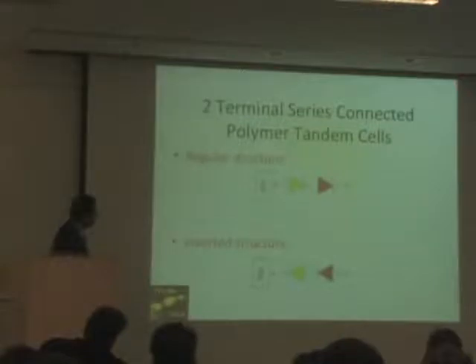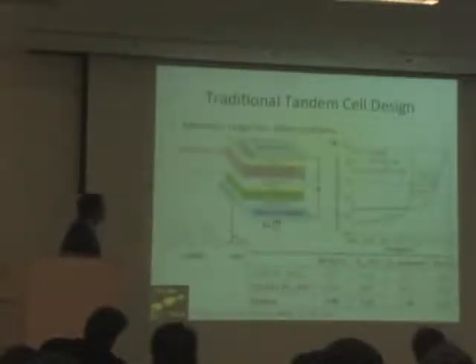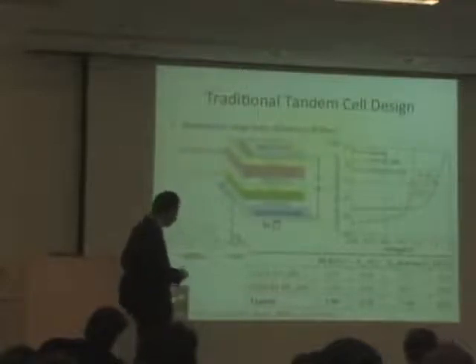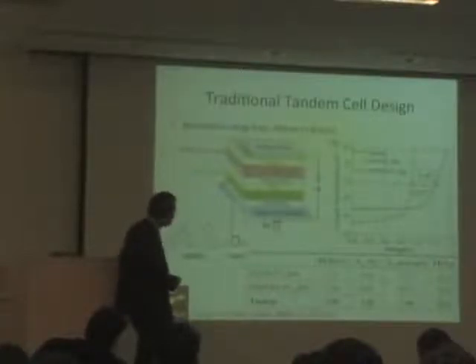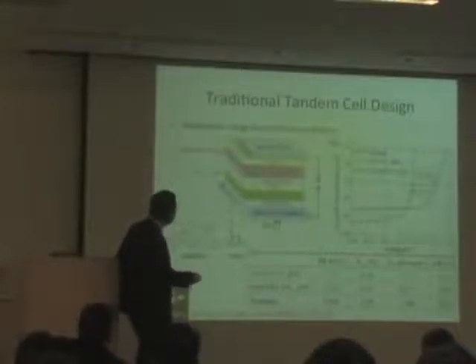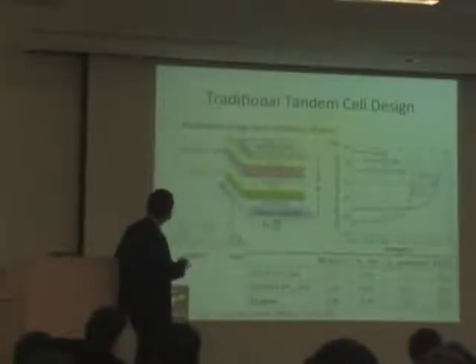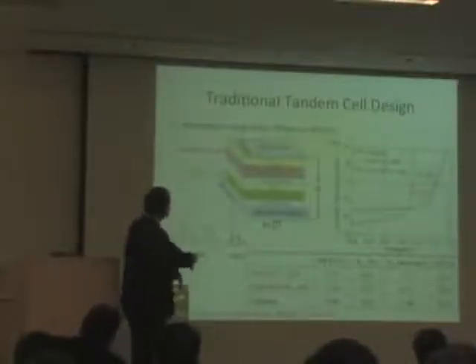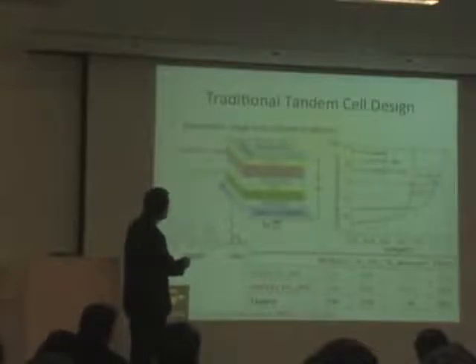Okay, so this is our regular tandem solar cell. This structure is actually rather similar to what Professor Heeger published in a Science paper. So let me start from the bottom. We have a glass and ITO substrate. We have PEDOT, a conducting polymer, and then this is P3HT:PC70BM. This is the active layer, the first active layer. So this green IV curve is the first solar cell. And the interconnecting layer is TiO2, titanium oxide processed by the sol-gel process, and the PEDOT. And then this is the PSBTBT. Remember I showed you the structure with the silicon here? So that's the second layer, and then the TiO2 doped with cesium carbonate on the top, and then the metal electrode. So you can see the IV curve.